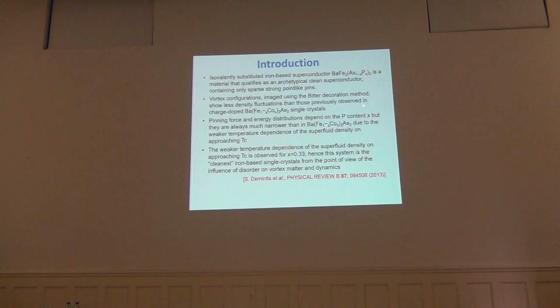Vortex configurations imaged using the Bitter decoration method show less density fluctuations than those previously observed in charge-doped Ba(Fe,Co)2As2 single crystals. Pinning force and energy distributions depend on the phosphorus content, x, but they are always much narrower than in the BaFe2As2 cobalt-doped single crystal, due to the weaker temperature dependence of the superfluid density on approaching Tc, observed for x = 0.33. Hence, this system is the cleanest of the iron-based single crystals from the point of view of the influence of disorder on vortex matter and dynamics. And these are the main things which come from this work by Demirdis et al., which was published a few years ago.